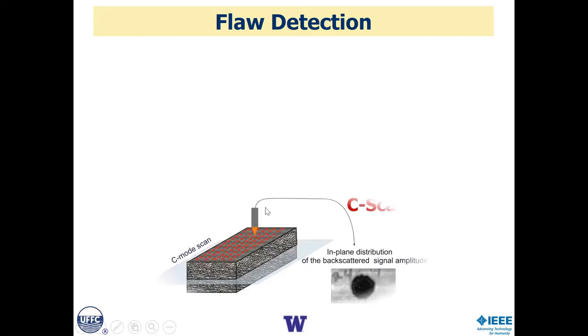Finally, we can raster scan the entire source and detector beams over the surface and get three-dimensional data. But the way we'll present this, at least for a biomedical person, is a little unusual. We'll present these as what are called C-scan images, that is, slices, horizontal cross-sections through the material. We show these as a movie, where time is running. As time runs on, you're going from the top surface of the material to the bottom surface. So with time, you're going through depth.